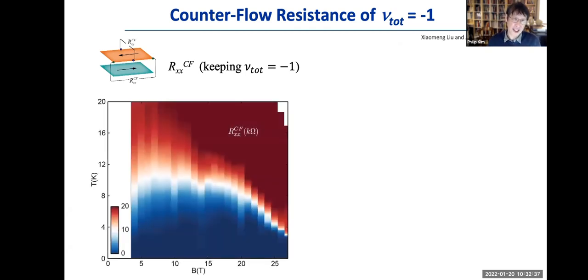Let me show you the data: graphene quantum wells separated by 2 nanometers of boron nitride, with an applied magnetic field. We just create this magnetic exciton condensation. And I'm showing you the resistance, or counterflow resistance, measured in this system as a function of magnetic field and temperature.